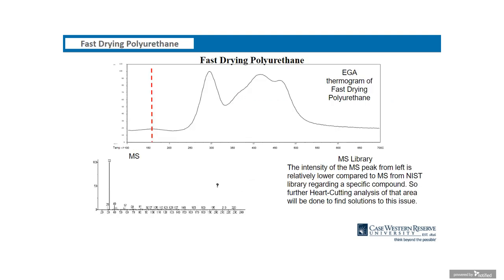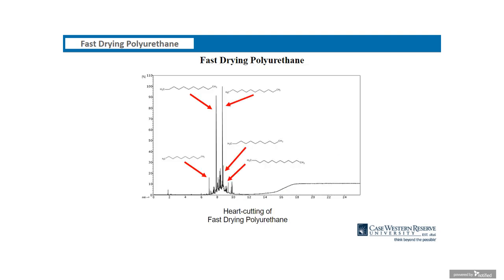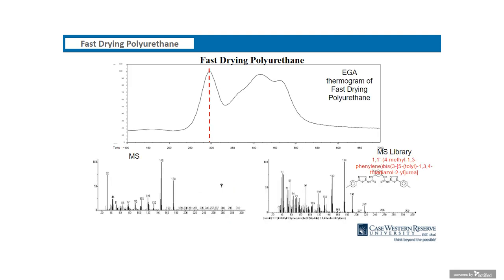hardener. So with the fast drying polyurethane, we confirmed several peaks here. We tried to see if there were plasticizers present or biocides. But what we found is this is a typical polyurethane composition. First, the heart cut confirmed the presence of these long chain polyol units. So this could be bio-derived.